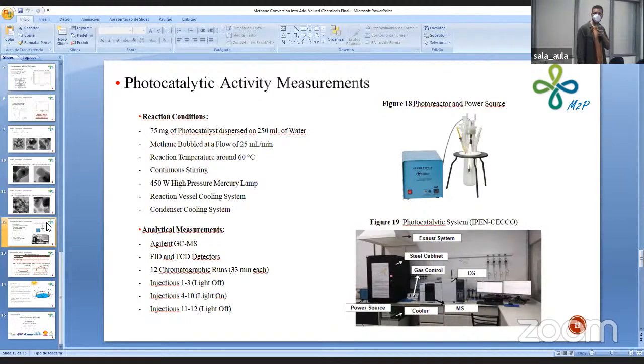As activity measurements, we use a photoreactor that is represented here at figure 18. In the test, 75 milligrams of photocatalyst were dispersed into 250 milliliters of ultra-pure water. Methane was bubbled in the system at a flow of 25 milliliters per minute. And as light source, we use a high pressure mercury lamp. And we can see here at figure 19 the photocatalytic system used.